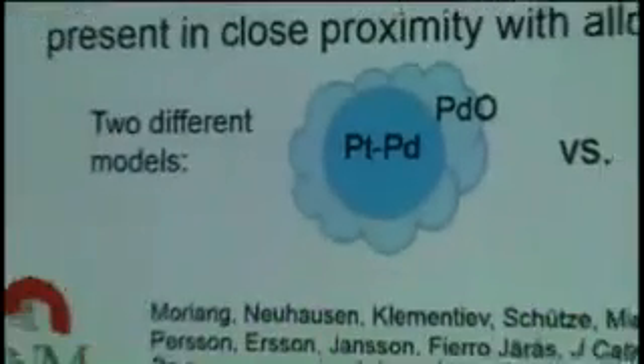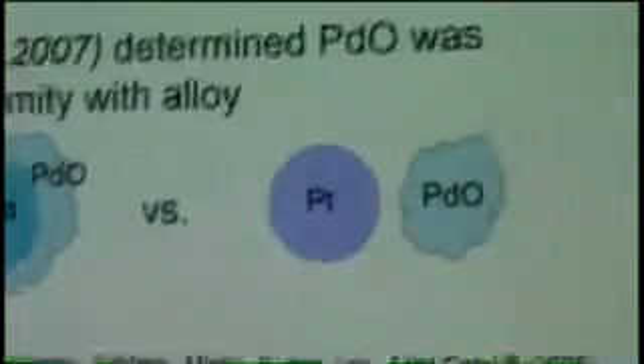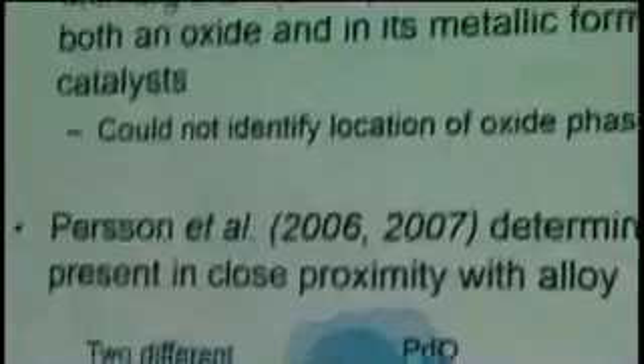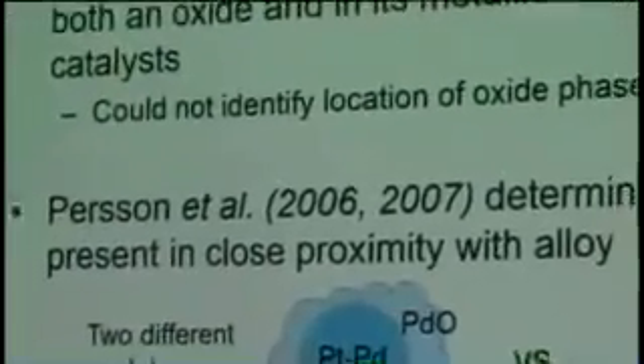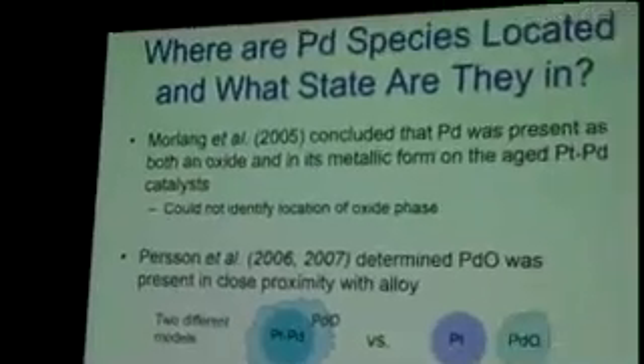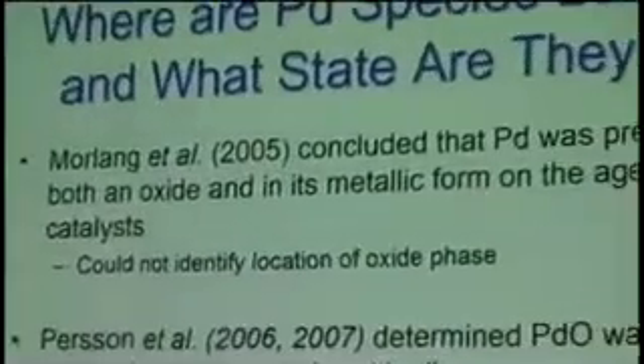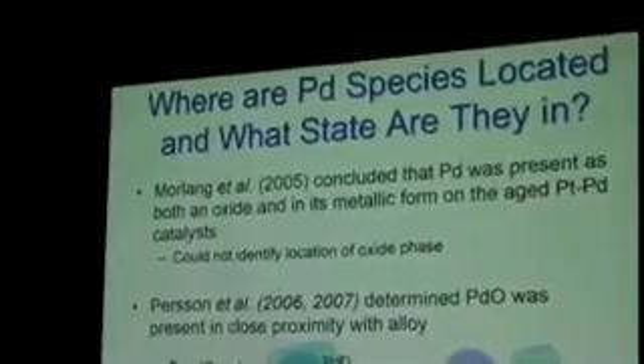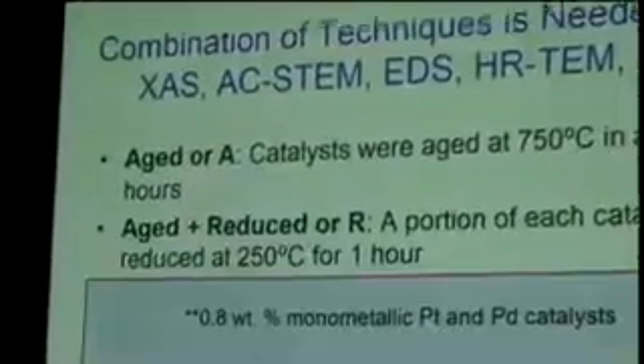Some of the literature is confusing. When you use bulk techniques like XAS, you may miss what happens on the surface of the catalyst. So when we started this work a few years ago, it wasn't clear whether in air the catalyst will oxidize and form a surface of palladium oxide. It wasn't clear that was really happening. Or whether it would be a phase separation. Both were possible explanations for what might happen in air when you heat it.